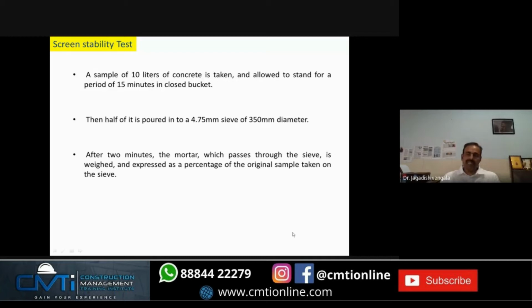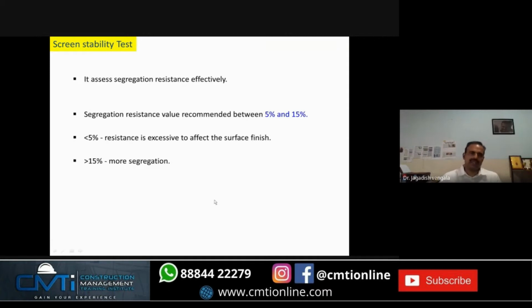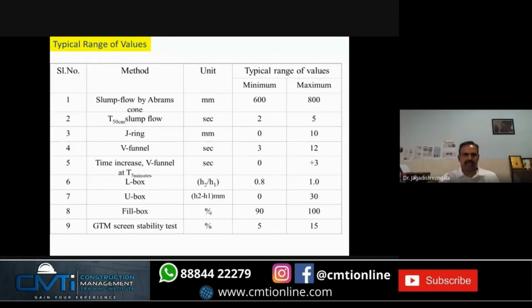What does that mean? If it is a good concrete, when you keep it for 15 minutes, the aggregate should remain there, that means on the top layer. If it is not good concrete, what will happen? All the coarse aggregate will settle down at the bottom of the bucket. So when you pick the top 5 liters, you have more of the mortar. So it should not be. When you measure, the segregation resistance recommended values are between 5 to 15%. It should be less than 5% if it is having more excess resistance. More than 15%, more segregation. That's what you do in the test.